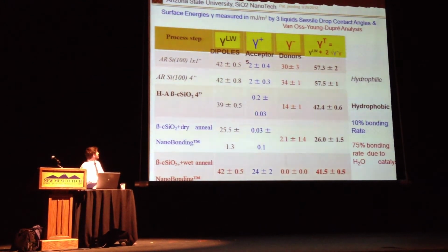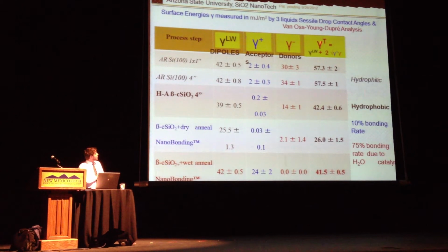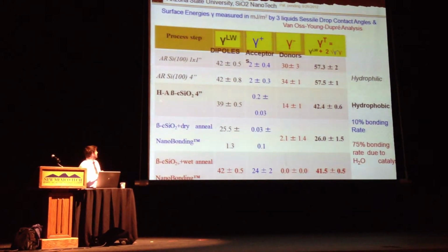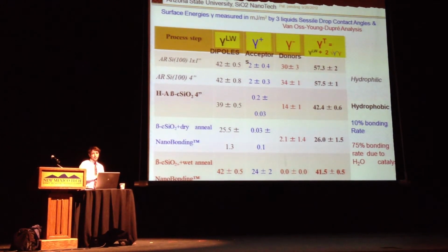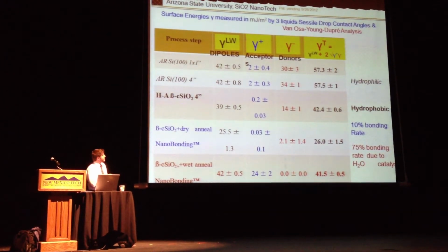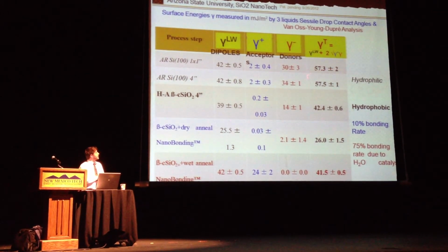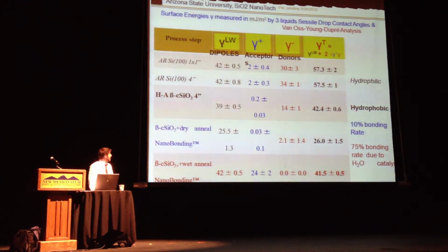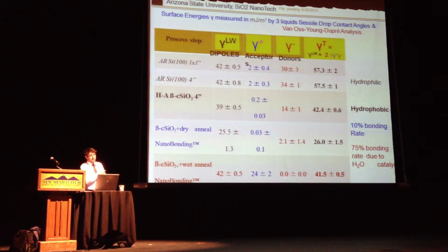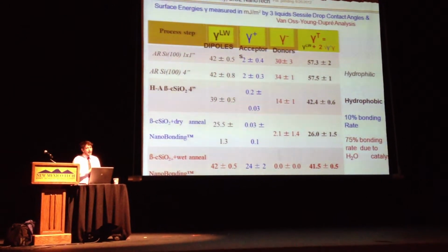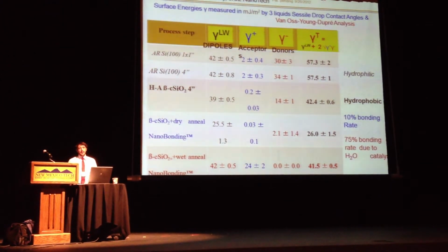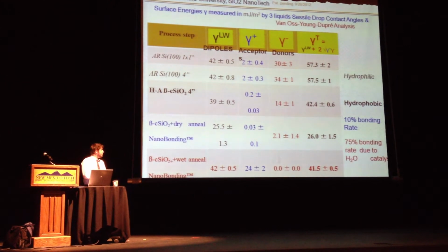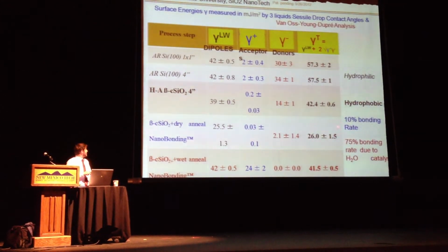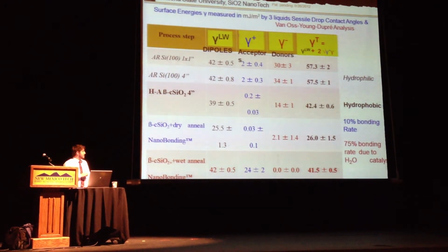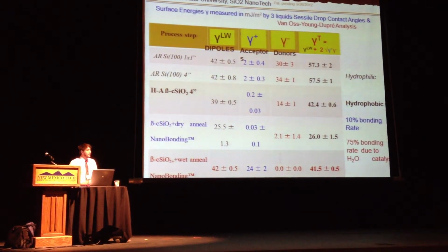In our comparison of before and after, we see that we have greatly reduced the surface free energy of this ordered SiO2 on the Si(100), so that's our precursor phase, compared to an as-received wafer, which has a higher value for the total surface free energy. This is all in millijoules per meter squared. Then we measured the actual characterization of the surface after a dry anneal and a wet anneal. The wet anneal, again, is the steam optimization for the humidity. We found a bonding rate of only 10% with the dry anneal, but the addition of the steam has increased the bonding rate to about 75%.